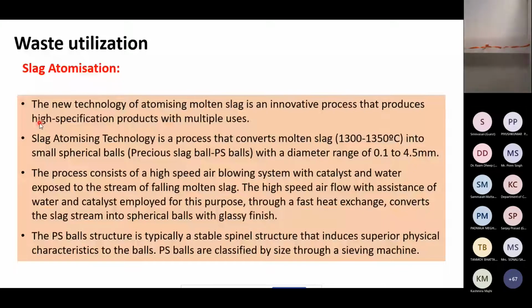The new technology of atomizing molten slag is an innovative process that produces high specification products with multiple uses. This slag atomization process is again a very costly process; integrated steel plants can adopt it, but small scale plants cannot. Slag atomizing technology is a process that converts molten slag at around 1300 to 1350 degrees centigrade into small spherical balls. These are known as precious slag balls or PS balls, with a diameter range of 0.1 to 4.5 mm.